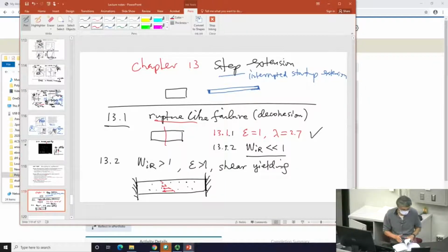Now I recall, even when we did the startup melt stretching, which also failed. Remember, in fact, I will come back to this many times in the future. An untangled polymer melt, when you stretch with a high rate, you can never succeed in keeping this extension homogeneous until it flows. Instead, the sample breaks, and one of the dominant features of breaking is shear.